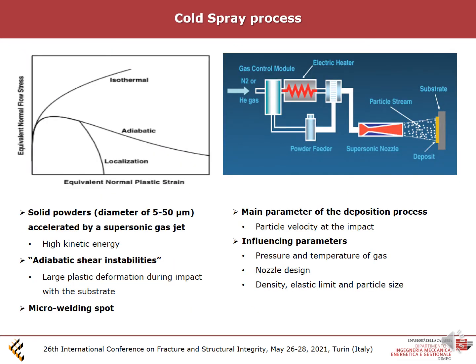Cold gas dynamic spray is a coating deposition technology in which solid powders with a diameter of around 5–50 microns are accelerated towards a substrate via supersonic gas jet. Due to their high kinetic energy, particles undergo large plastic deformation during the impact with the substrate, and the consequent adiabatic shear instability provides material flow and heat for bonding. And these mechanisms actually represent the main driving force for the adhesion and cohesion of the coating. In fact, the term cold indicates that maximum temperature reached during the process is below the melting point of the